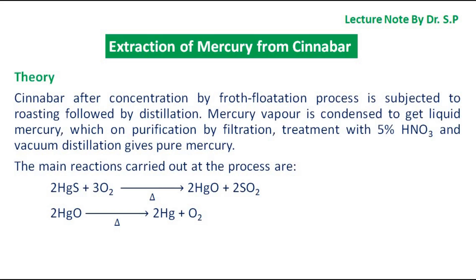Extraction of Mercury from Cinnabar: Cinnabar, after concentration by froth flotation process, is subjected to roasting followed by distillation. Mercury vapor is condensed to get liquid mercury, which on purification by filtration, treatment with 5% nitric acid, and vacuum distillation gives pure mercury.